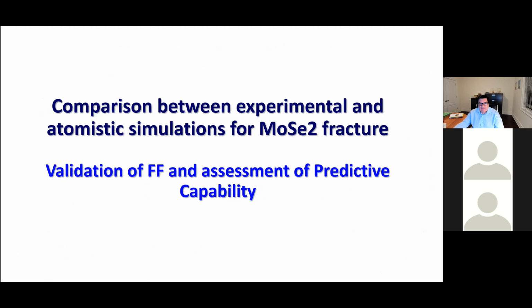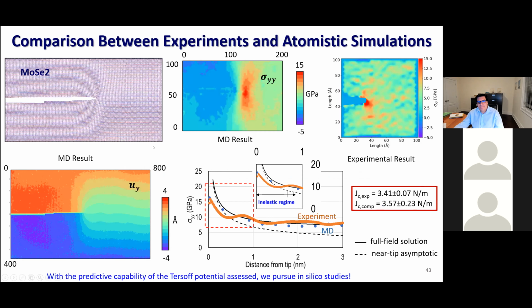So let me go back to our fracture problem. We have the experimental data, now we have a parameterized force field with a certain degree of confidence, and we want to assess the predictive capability. In other words, we want to compare the toughness predicted by the molecular dynamics simulations using the J integral concept, again, the area integral implemented in MD, versus the experimental measurement. And the conclusion is that the two come very close. We didn't fit the force field any more, we didn't do anything, and it predicts very reasonably the J integral.